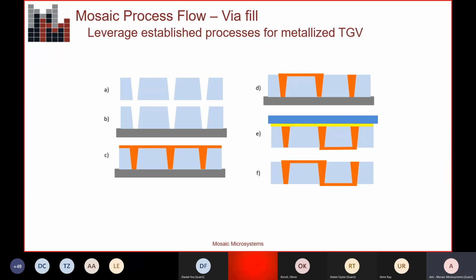So how does this really enable via metallization? I spent a lot of years trying to optimize how you fill vias in glass. A lot of times the through glass vias are hourglass shaped just because of the nature of the laser and etch process, which is a pretty standard approach for glass. What Mosaic does is take pains to not have an hourglass shape, but to have a more tapered via to make it look like a blind via in TSV, for example.